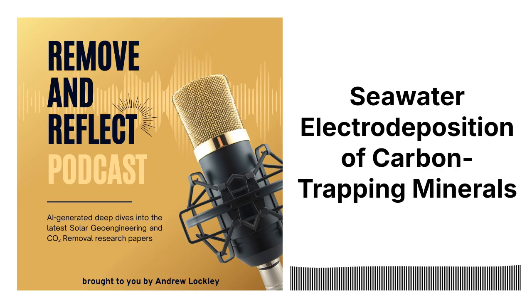Exactly. Okay, so we're putting all this energy in, we're injecting CO2, and we're getting these minerals out that are locking away carbon. But fundamentally, what are these minerals that we're producing? Through some high-tech analysis techniques like X-ray diffraction and thermogravimetric analysis, the researchers were able to determine that the primary mineral components were calcium carbonate, which appears in two common forms called calcite and aragonite. The other main component was magnesium hydroxide, also known as brucite. So could they control which of these minerals ended up forming?